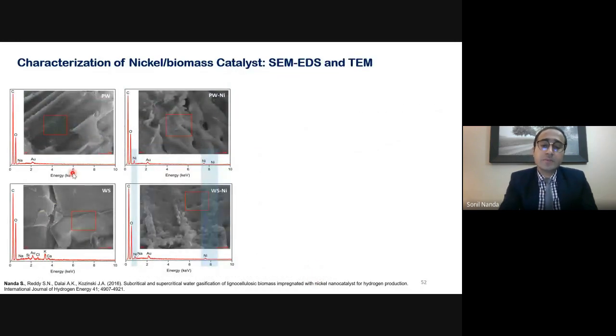Now, we also did some confirmatory studies to determine how well the nickel was impregnated into the feedstock. PW indicates pine wood and WS indicates wheat straw. These are the two control feedstocks you can see, and this is the SEM-EDS, energy dispersive spectroscopy analysis.